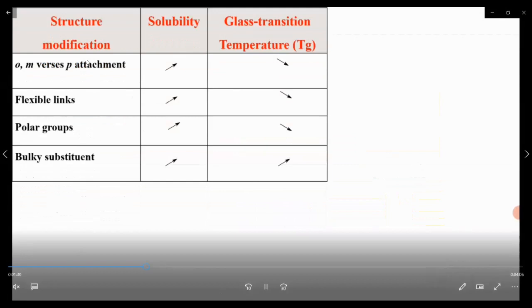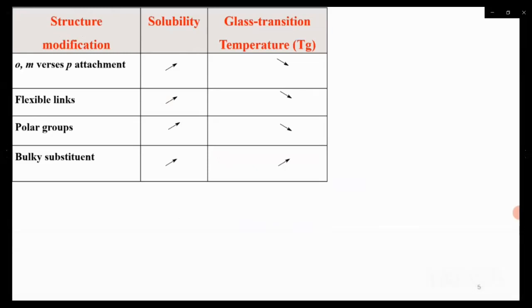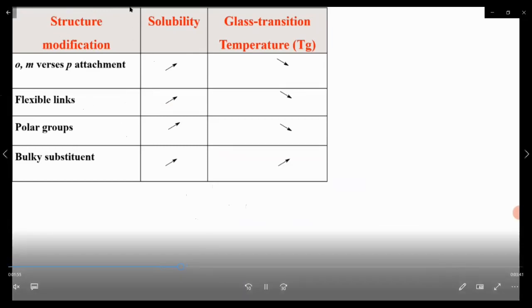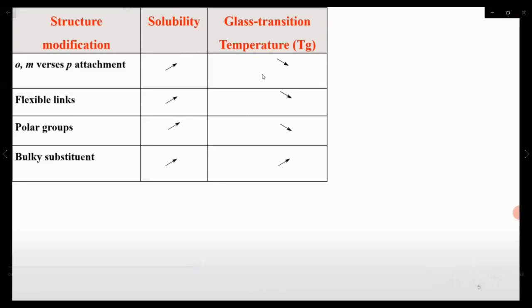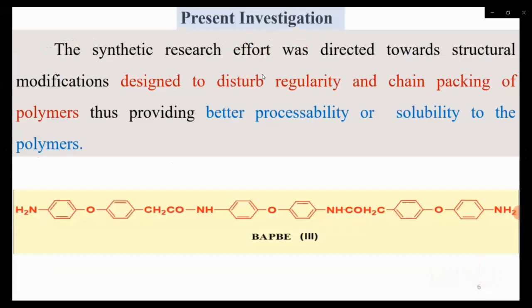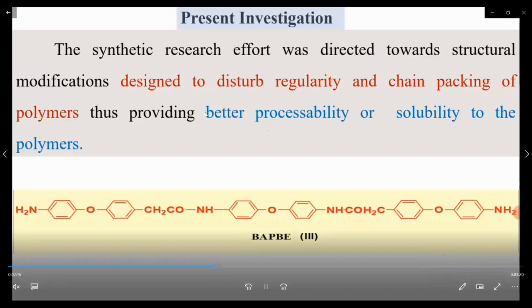So worldwide efforts are directed to increase the solubility of polyamides by structural modification of the polymers. It can be achieved by incorporating flexible links like ether and methylene groups into the polymer backbone. This reduces chain packing and allows free rotation of the polymeric chain, so that the polymer chain packing is reduced and the polymer can become soluble or processable. In this present research work, our efforts are directed to modify the structure of the monomer by disturbing the regularity and the chain packing, to provide better solubility and processability to the polymers.